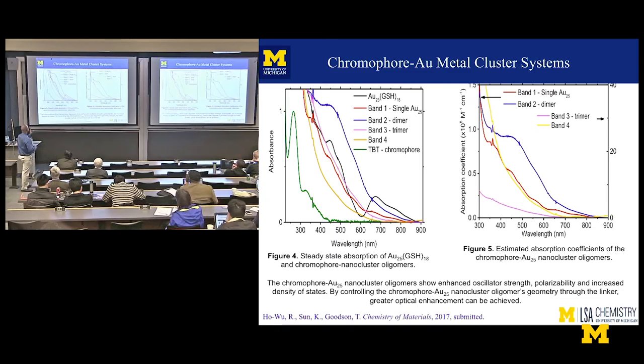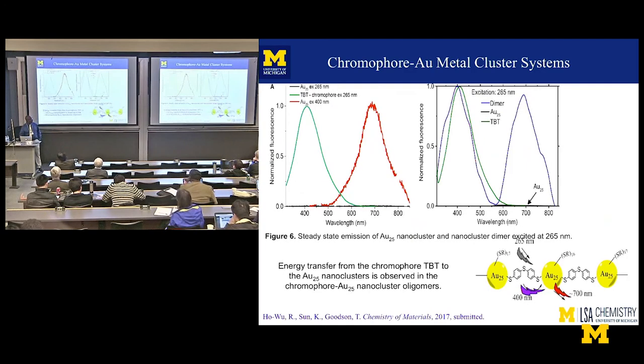We made these things, and now you have a gold cluster, dye, gold cluster topology. You have dimers and trimers. You can look at the absorption and see where the dye was absorbing. You can look at the absorption coefficient for the different things that you made. For example, band one is just the gold cluster, but band two has the gold cluster, the dimer, if you will, and then other structures. So from an absorption standpoint, it looks like you made a lot of gold dimers. Again, you can look at the emission, the normalized fluorescence. Rosina did a very nice job.